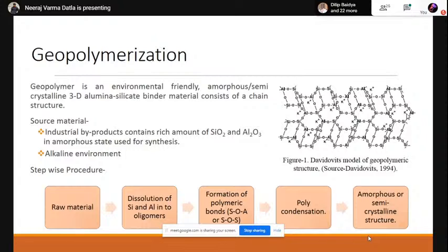Coming to the procedure for geopolymerization, when we add this silica and alumina rich material in alkaline solution, silica and alumina tetrahedral units get separated from the rest of the raw material, and then with the help of oxygen atoms, they share silica and alumina atoms. Likewise, they form a polymer network, and slowly the polymer chain will polycondensate, and finally we have an amorphous or semi-crystalline structure. It is similar to zeolite, but the only difference is it does not go up to crystalline.